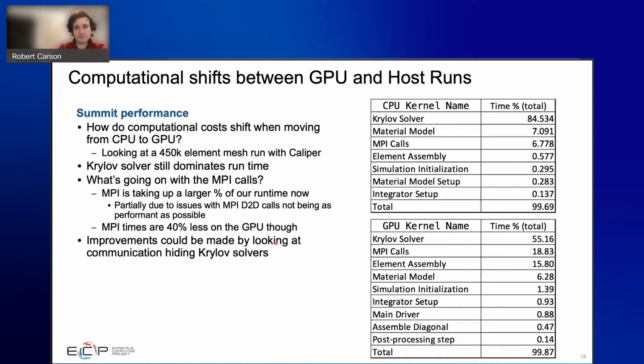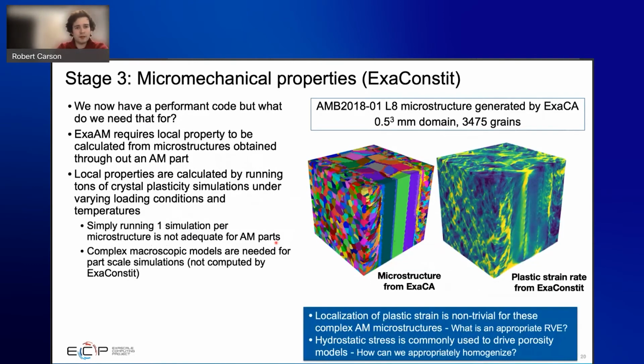So now that we have this nice performant code, what are we going to use it for? What do we really need it for? Within ExaAM, I've mentioned that we need these local properties to be calculated throughout our parts. Each one of our local properties calculations requires us to run a ton of different crystal plasticity simulations under varying load conditions and temperatures. We really can't get away with just running one simulation for an AM part. If we look at our deformation field over here, it's very complicated. There's a lot going on, and the response from our material is anisotropic, so it's not a nice isotropic behavior where you can assume the response is equal in all directions.